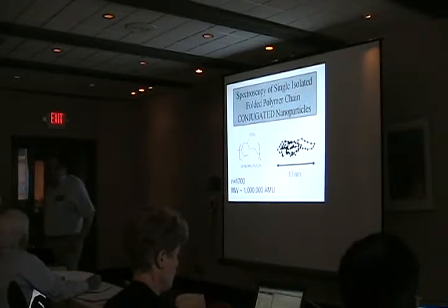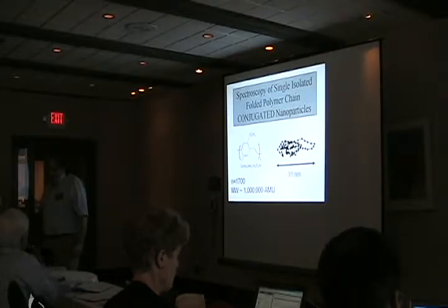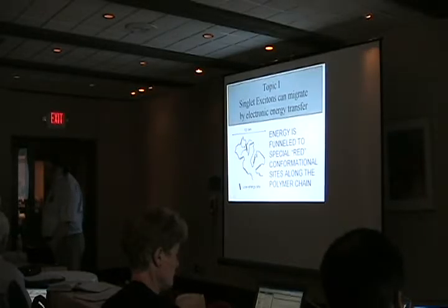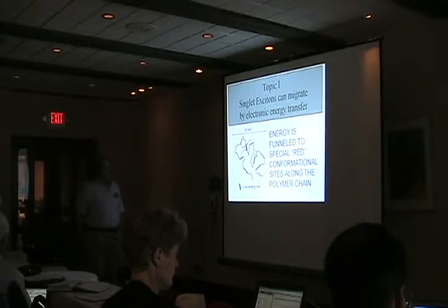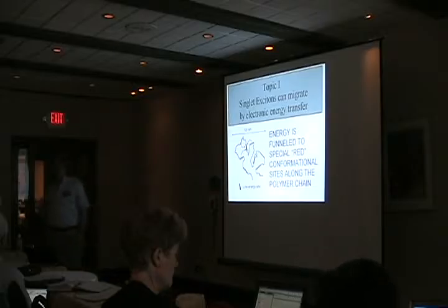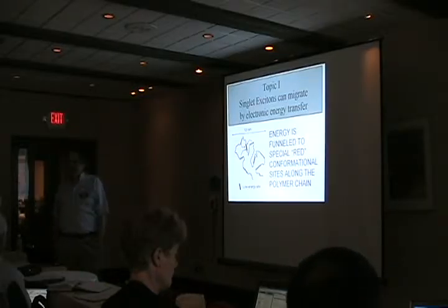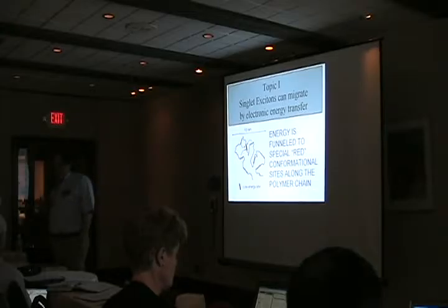Just very quickly, the conformation of these polymer chains was the first thing we got interested in the late 1990s and early 2000s, and this led to a very non-orthodox theory that Peter Wolynes, Bin Baji and I put forward, borrowing some ideas from outside of polymer physics, from biology, about a particular cylindrical type of conformation, which I think is now generally accepted. And because of this effect, what happens in these systems, if you have just a single polymer chain that's not too big, let's say of the order of molecular weight 1,000, is that there exists a Poisson number of low energy sites that have their energy shifted quite off from the main band of states due to some packing interaction in the chain. So let me explain what I mean by that.